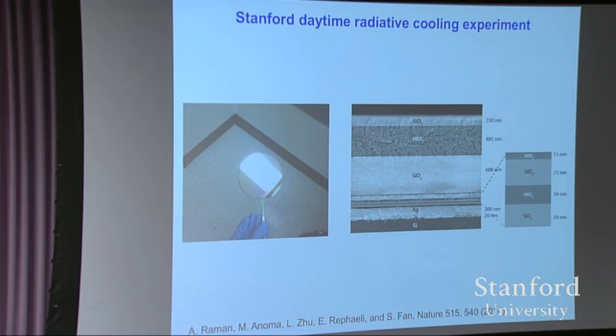How much more difficult was it to make the photonic structure out of the silica as opposed to the planar surface? You mean for the radiative cooler structure, the beginning structure that I showed? Silicon is completely inert in this, so it's just convenience. In fact, the functional structure is from silver up. The rest are just substrate. It happens that when you start, you look for the most convenient place to fabricate your structure, and fabricating on silicon is most convenient. There's no intrinsic reason for doing so.